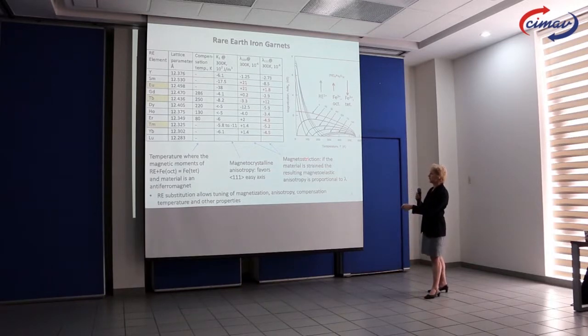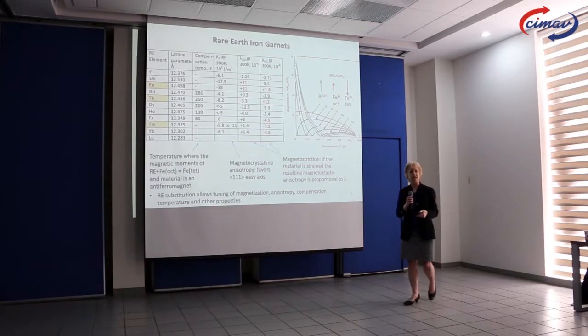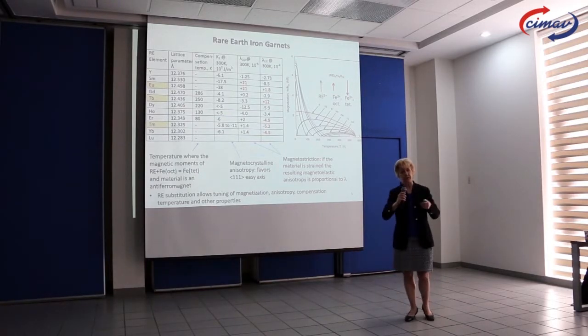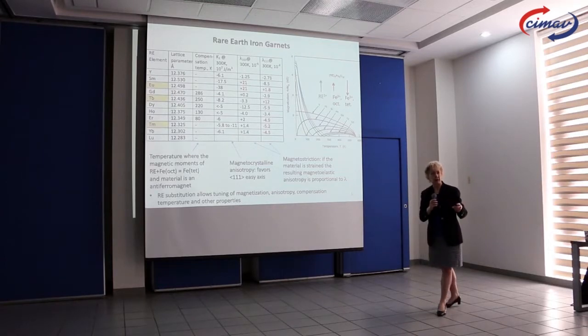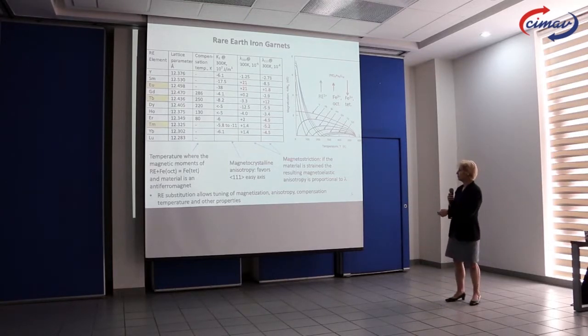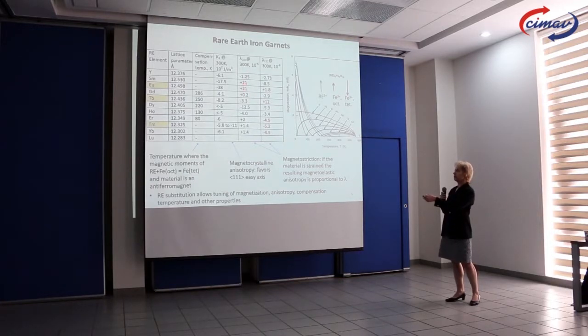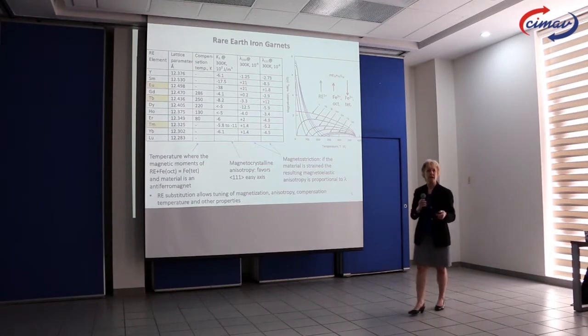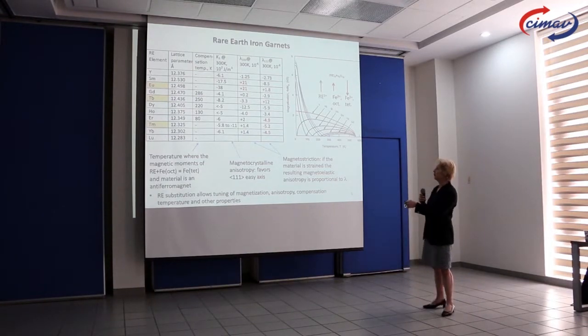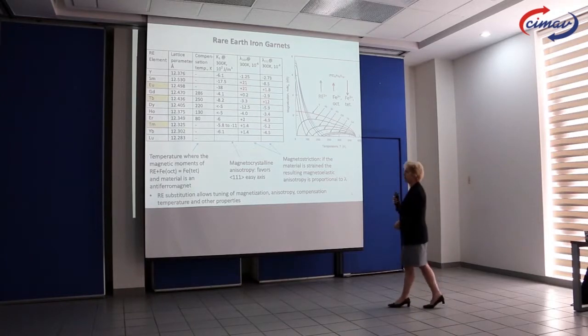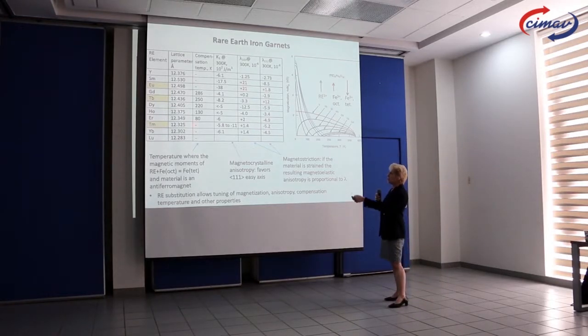We get changes in magnetostriction, and this is an important parameter for us because this is the parameter that tells us what happens when we strain the material. If we put the material onto a substrate where it's strained, then we will get some magnetic anisotropy, and the anisotropy depends on how big this number lambda is. So some are negative and some are positive, some are large and some are small. So this is a way we can engineer the properties of the garnet by choosing one which has an appropriate magnetostriction. And then finally, the ones in the middle show a compensation temperature.